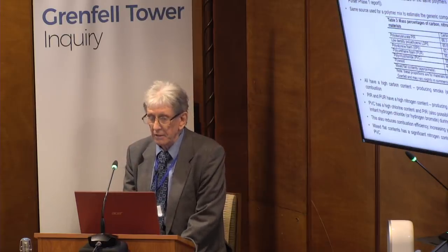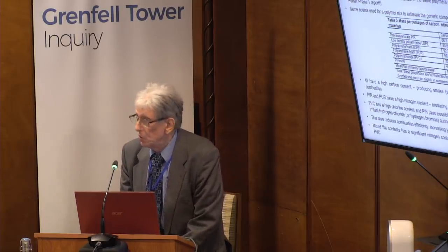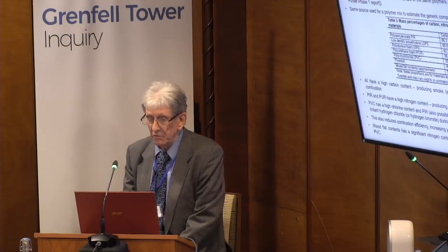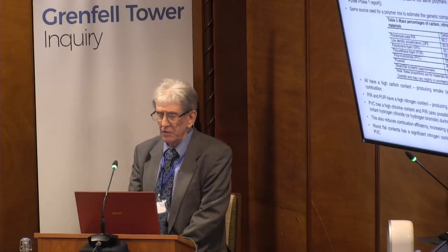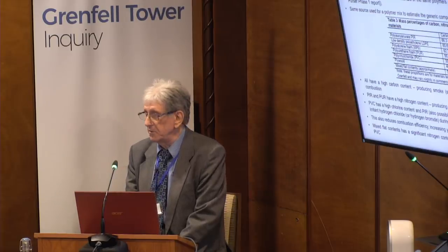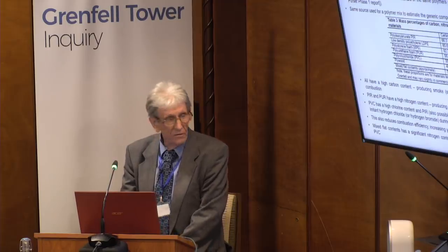In plywood and MDF, things like that, it's not pure wood. You have certain resins and things in, but you also have a little bit of nitrogen, as you can see there. So for the mixed flat contents, taking all the sorts of things you'd find in a flat, my estimate is overall about 50% of the mass being carbon and about 3.7% nitrogen and a little bit of chlorine.